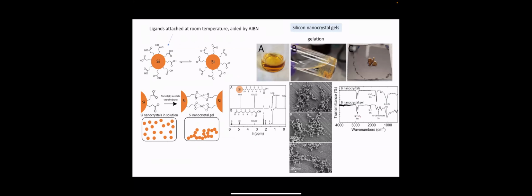We've been doing a lot of things where we want to do hydrosilylation at room temperature, and one way that actually works pretty easily, depending on your solvent system, is you can add AIBN, and this works pretty well. You get a covalent silicon carbon linkage. So this is some additional work from Ben making gels of silicon nanocrystals. We can passivate with a carboxylate group, and then we can disperse these in water and ethanol, and add nickel ions, and the nickel will cross-link the carboxylate groups, and you can make gels that way and things like that.